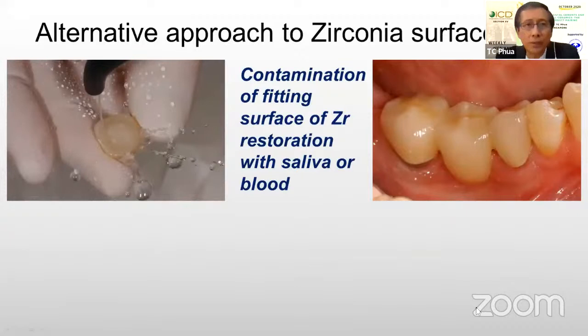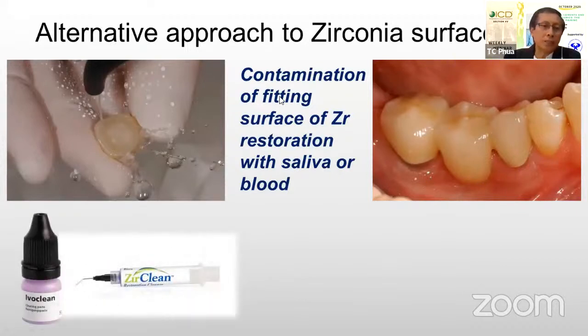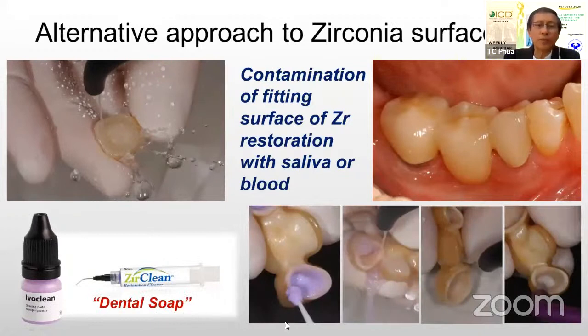So an alternative approach to zirconia surface prep, if you do not have the ability to air abrade, is to use some kind of a dental soap, for example. Because what happens is that when you try in all these zirconia crowns, it gets contaminated with blood and saliva. And there are two distinctly new materials on the market here, Ivoclean from Ivoclar Vivadent, and Zirclean from Bisco. What it does is like a dental soap that you can apply onto the fitting surfaces of your crowns,